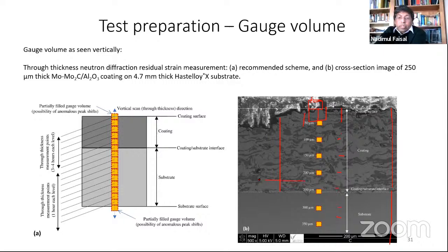Now the interface is important. If your point is here, you may get a lot of overlaps coming from the coating and the substrate. If your point is here, you may get largely coating and a little bit of substrate. So this is some of the thing to worry about at the start of the experiment, because once you set the experiment, it will run for hours.